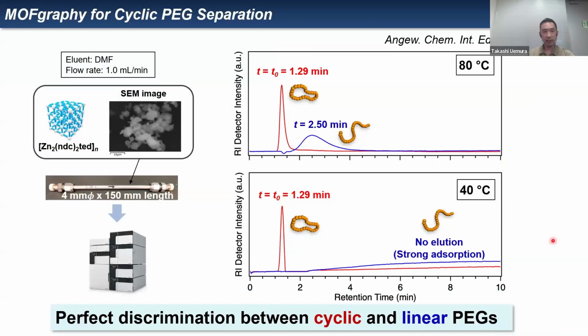So MOFography can do the perfect discrimination between cyclic and linear polymers, just with simple temperature modulation like this. At lower temperatures, linear PEG is adsorbed strongly, but cyclic polymers are eluted very quickly because this polymer is not adsorbed in the MOFs.